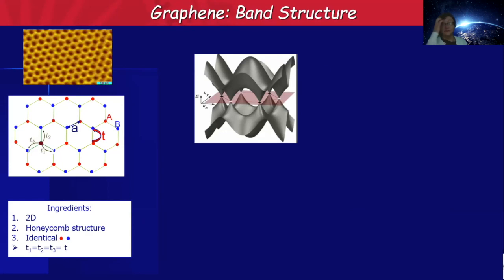So first of all, what are the ingredients that went into this band structure? There are basically three ingredients: the fact that the material is two-dimensional, the fact that it's a honeycomb structure, and the fact that you have identical atoms on the two sublattices A and B, they're both carbon, and also that you have identical hoppings between any atom and its near neighbors. So that gives you this band structure here.